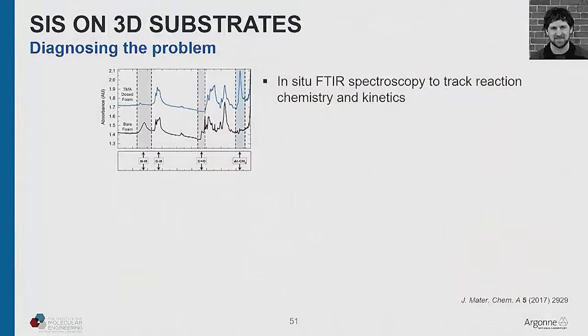So here we turn to a little bit of science. We were able to do in situ infrared spectroscopy in this system, so we can track what's going on a little bit. So I know you can't see it all that well back there, but this is the infrared spectrum of the starting foam. And here's a feature that corresponds to the NH feature of polyurethane, and here's one that corresponds to the carbonyl groups, which are also in polyurethane. After you expose it to TMA, you'll notice that those two features all but disappear. Those are the functional groups in the polymer chain that are interacting with the precursor, the SIS precursor.